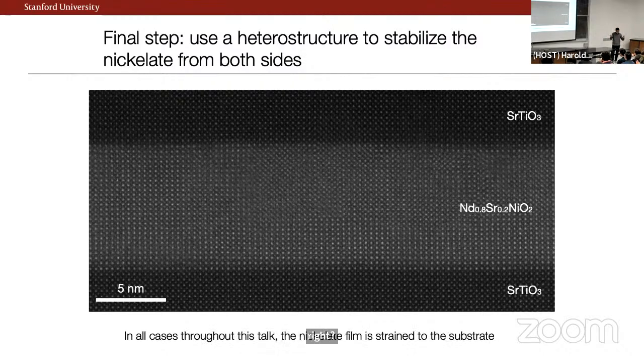And we're quite proud of this kind of a sample, which shows nominally a crystalline phase, which we know what we're measuring. And I'll give you some of the basic properties of this. But what's also true is that this is kind of the maximum thickness or volume film we can grow where we have complete control. It's not very big, right? You can see it's typically 10 to 15 nanometers. So one of our experimental challenges is how can we study what we need to study limited by this situation, right? I only give you 100, 150 angstroms thickness of some material, looks exciting, you know, how can we probe and understand it? So that's kind of what I'll tell you about.